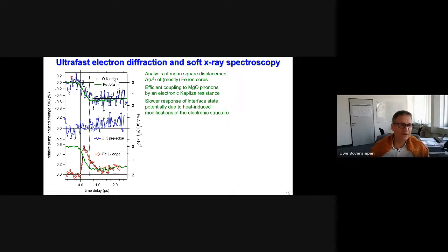And here on the top diagram, I did this. So this is a second scale where you see the mean square displacement of iron. This is the green line, and it matches pretty well what we observe with soft X-ray spectroscopy at the oxygen K-edge. So think a moment about the situation. We excite electrons in iron. There's electron-phonon coupling, which determines the green line, the mean square displacement. And on that very time scale, we see already a response at the oxygen K-edge. So this means that there's extremely efficient coupling through the interface to the excitations in the insulator.